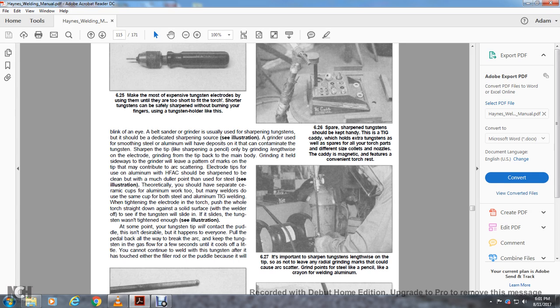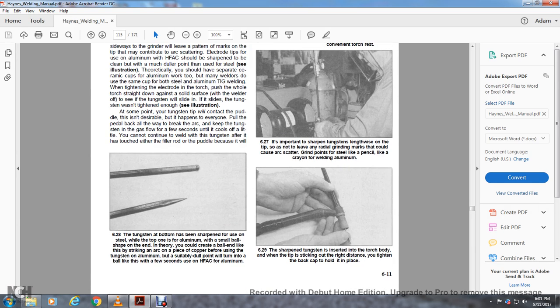627. It is important to sharpen the tungsten lengthwise on the tip so that it is not leaving any radial grinding marks that could cause the arc to scatter. Grind points on steel like a pencil, and like a crayon when welding aluminum.